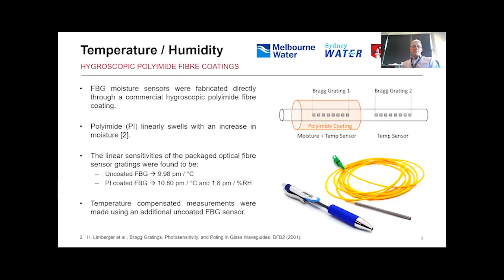And there's some of the metrics at the bottom there. So we see about 10 picometers shift per degree Celsius and 1.8 picometers shift per percent relative humidity.